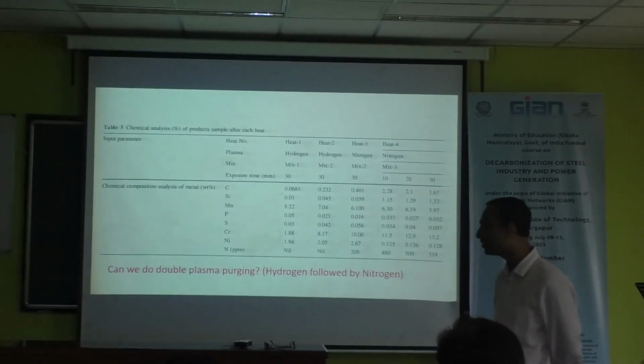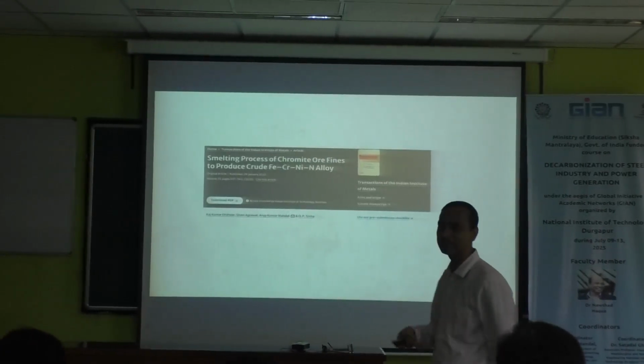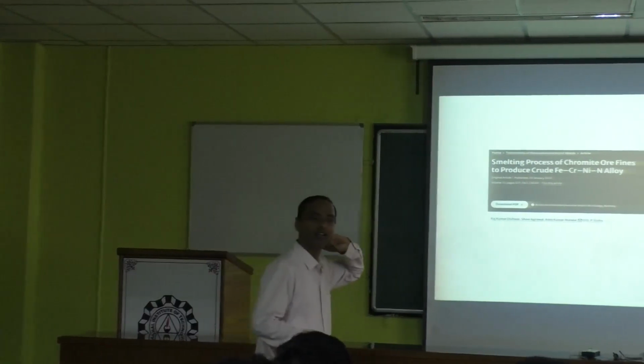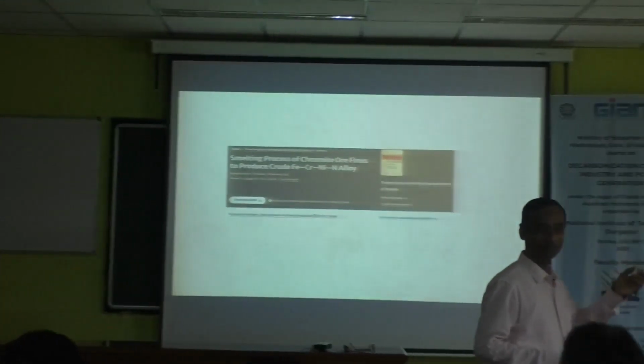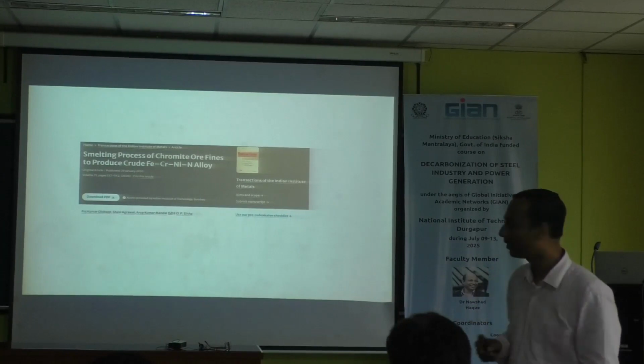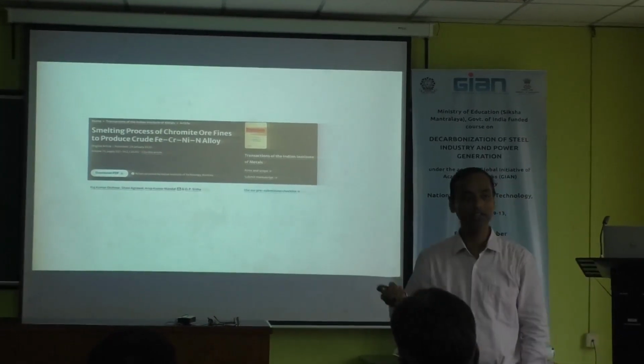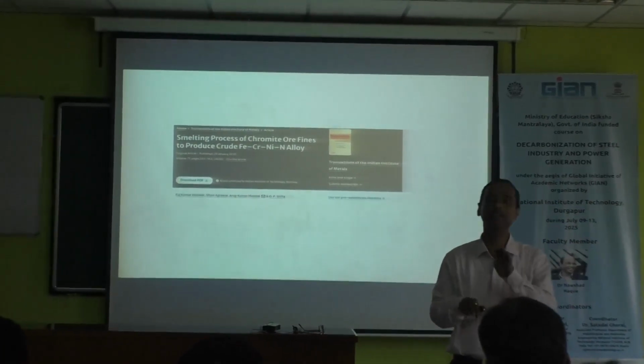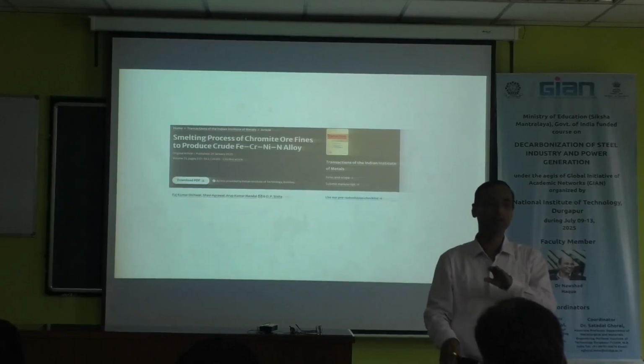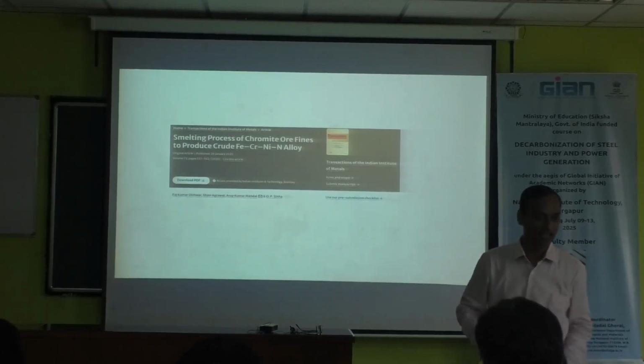And it will give you the grade of stainless steel. Actually, in this paper that we published, we proposed this. We prepared the crude stainless steel grade, but at that time we actually did not think about using hydrogen plasma for reduction. But when we introduced the hydrogen plasma in these cases with the students, then we understood that if we introduce both plasmas, initially hydrogen plasma, that will be great. After that, switching over from hydrogen to nitrogen, we will get, as per our requirement, the stainless steel directly.